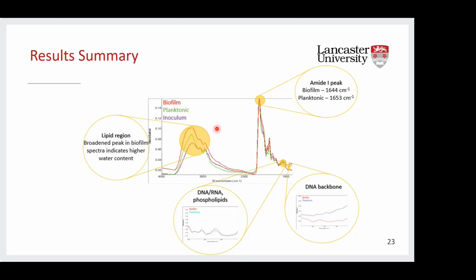Now, the most important differences are actually seen in the lower half of this spectrum. Firstly, I'll draw your attention to the amide 1 peak. This definitively shifts, so you have different proteins existing in your biofilm compared to your planktonic sample. If you think about it, this is quite logical, because with the biofilm you have that extracellular matrix, which we already know contributes these new proteins. Then again, if you move down the spectrum, you see this peak at 1082 wave numbers. Here you see a shift in the peak, but also a change in the shape. And again, this is just alluding to fresh proteins in our sample.